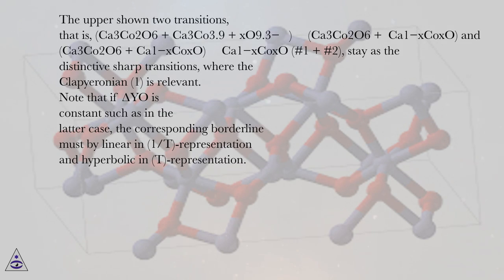Note that if ΔYₒ is constant, such as in the latter case, the corresponding borderline must be linear in 1/T representation and hyperbolic in T representation.